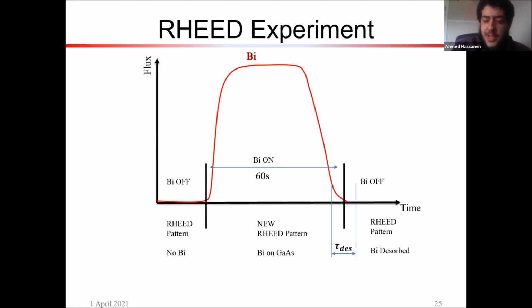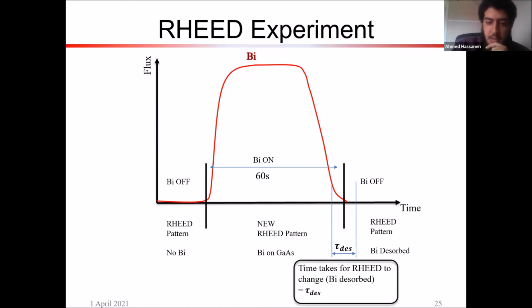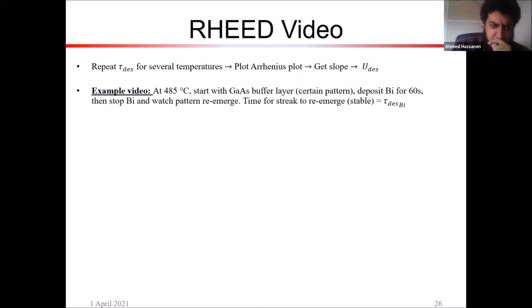And so the time it takes to change between this new RHEED pattern and the old RHEED pattern is an estimate of the desorption time, because this is a manifestation of how the bismuth is desorbing. And so basically that's the essence. This is the gist of what we're going to do with this experiment. And so if we repeat this experiment for different temperatures, we can again get the slope as we mentioned.